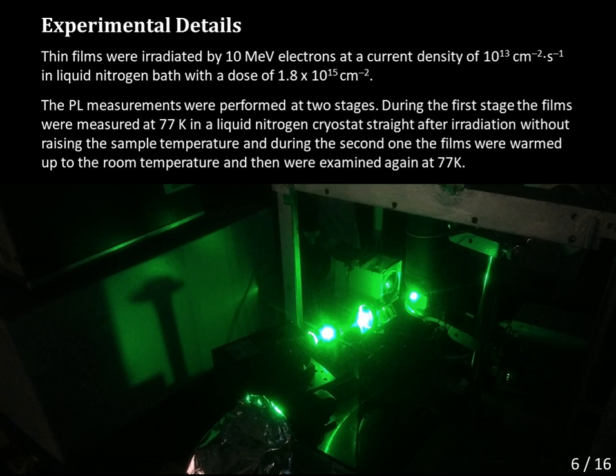Thin films were irradiated by electrons in liquid nitrogen baths. The photoluminescence measurements were performed in two stages. During the first stage, the films were measured in the liquid nitrogen bath straight after irradiation without raising the sample temperature. During the second one, the films were warmed up to room temperature and then examined again.